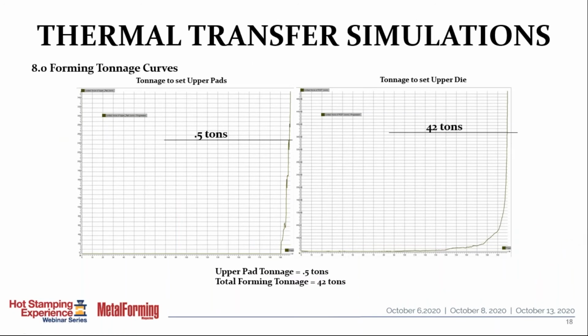We also, through the simulations, help establish tonnage curves for pads and for forming. And those are important to help size the pad pressures and to come up with a minimum tonnage that we believe we should be able to form the tool in or form the part in. That helps us validate that the tool can run in a certain press, and also gives us a starting point for tryout to see if we can get to bottom of stroke with that tonnage.